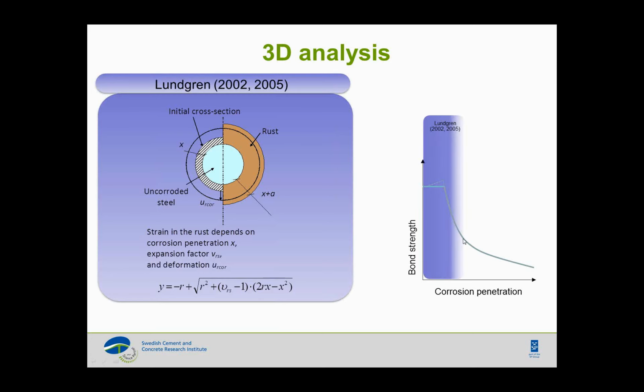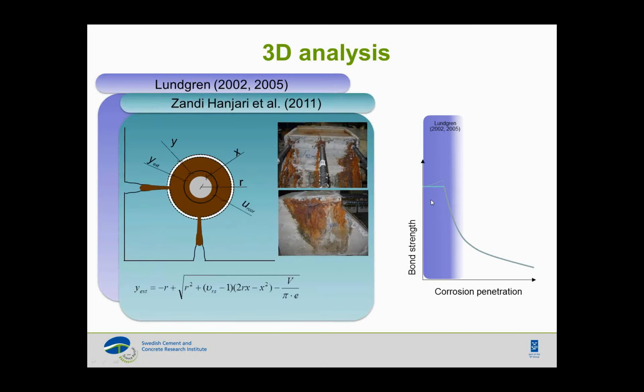And we think that if we use the original corrosion model, we can capture what happens around the first cracking, but it's hard to move any further because we get to large crack widths and we come into numerical problems. So when we added this effect with rust flowing out through the cracks, we managed to go a little bit further in the analysis. Now we can go for higher corrosion penetration, and coming to a case where we look at lower bond strength values.